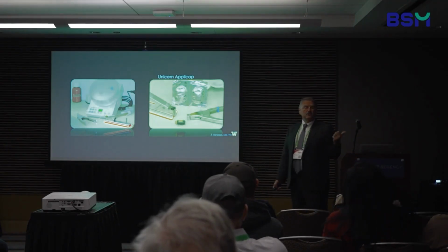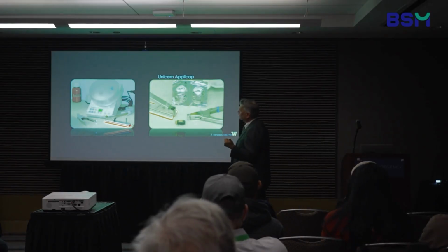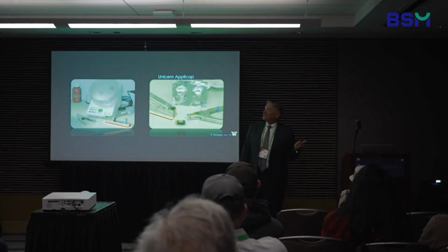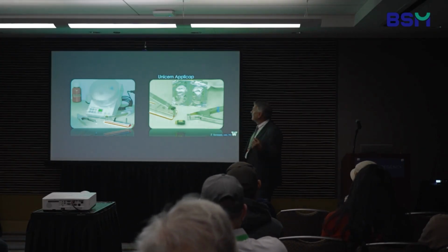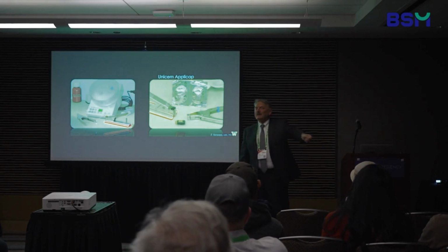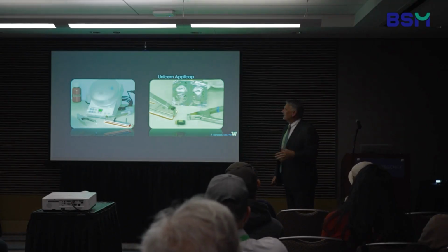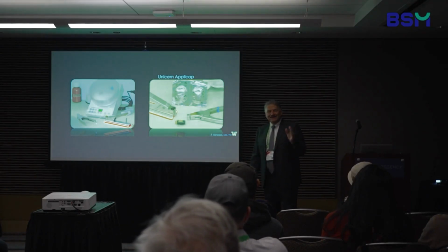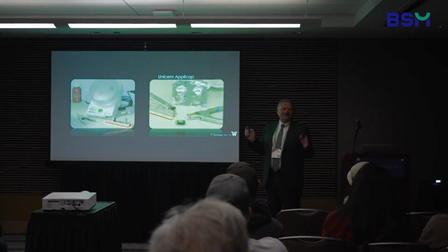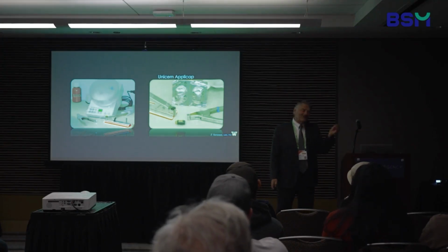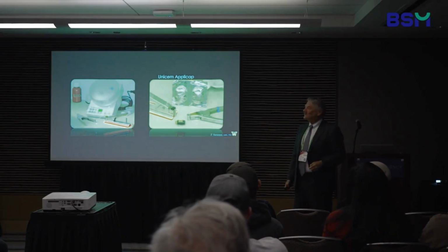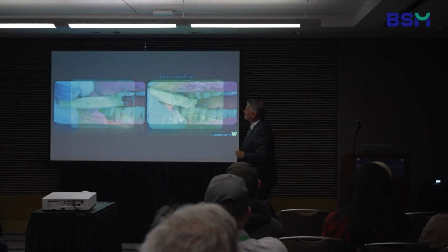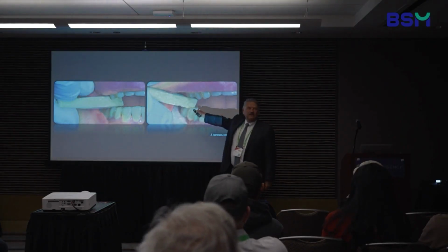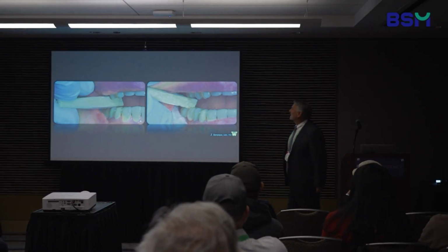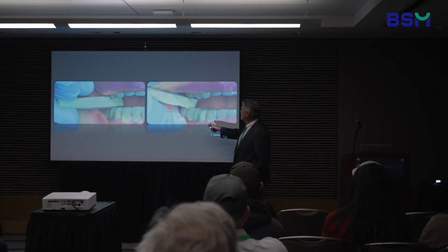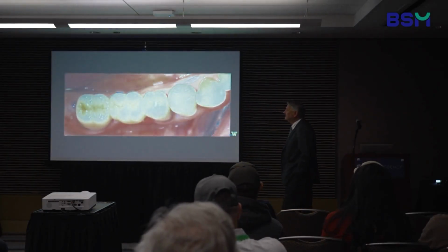All we want to do is either aluminum oxide abrade the surface with 2 bars for the zirconia, or use the IvoClean material, which you just paint on there for 20 seconds and clean it. So whenever I lectured for laboratories, they always go, Dr. Sorensen, you have to talk about cements because the doctors are always asking the labs, well, how do I cement this and so on. So again, a very simple process, and strong enough that I can use the dynamic seating method as described by Gegauff and Rosenstiel to get this seated all the way down into place,